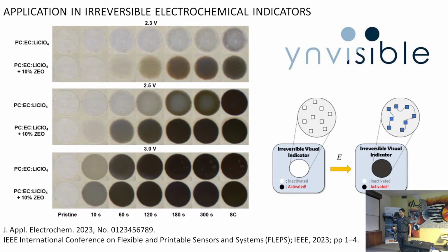Okay? And indeed, she did a lot of work with this and tested several formulations, especially of the electrolyte. And for instance, in here, you can check out that when you apply 3 volts to the label, it really goes from white to black in about 5 minutes. Okay? And this is a huge color contrast, and then it can be used as an irreversible visual indicator, and it's part now of the portfolio of the technology owned by this company.